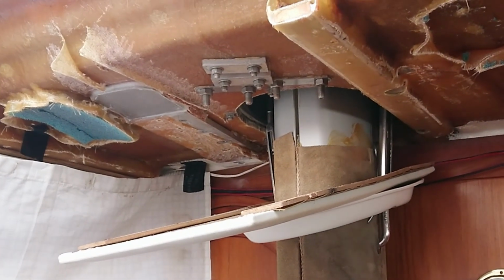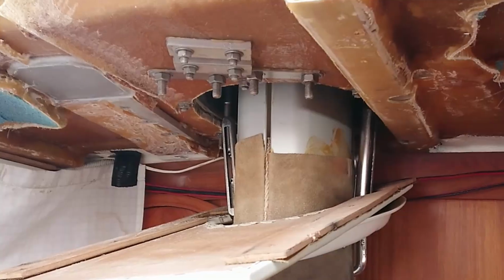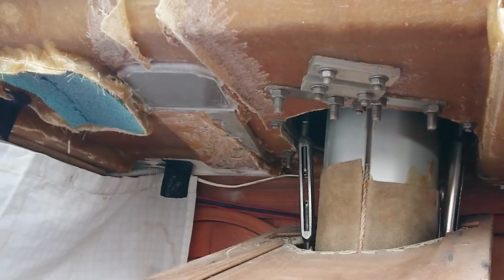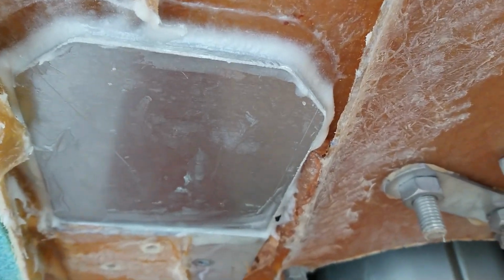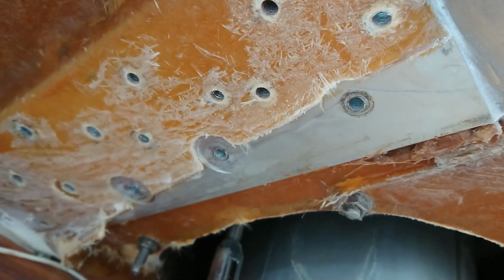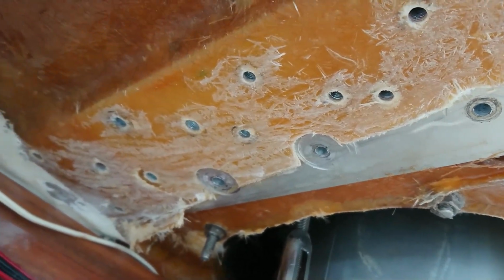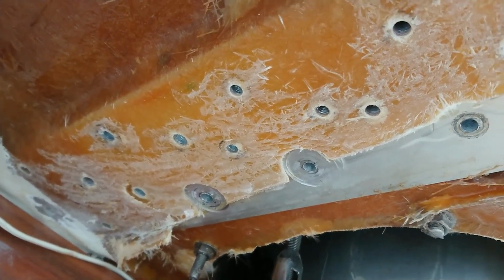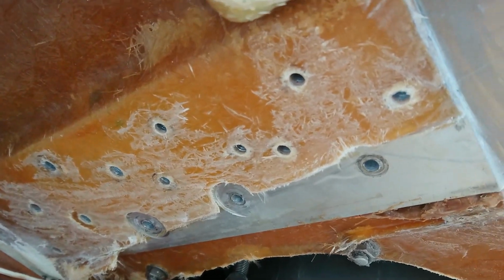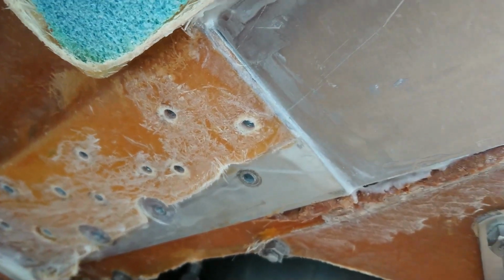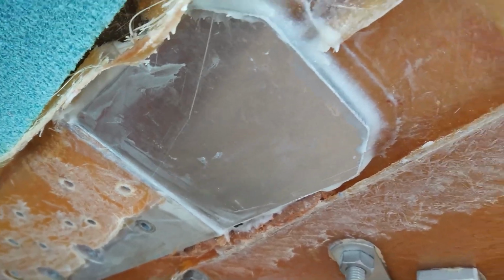We've now got all the holes drilled out to 14mm, and I've fitted that backing plate underneath where the new block's going to go. I've used a piece of 8mm thick aluminium plate cut to shape and epoxied it into place using resin thickened with colloidal silica. You can see the new plate sits flush next to the old one with the pre-existing 6mm and 8mm holes for the bolts to go through.